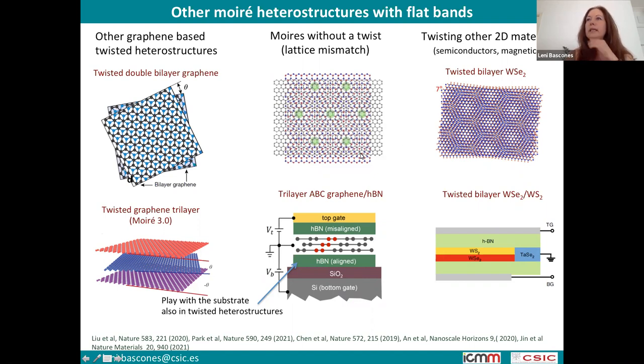One can do moirés in a different way, in which you don't have a twist. In particular here, what is used is that you align the graphene with boron nitride, so the lattice constants are very close, but not exactly equal, and this is another way to build a moiré. And you can also use other 2D materials which are not graphene, like here, these are the chalcogenides, in which the two layers can be equal, or they can be different.